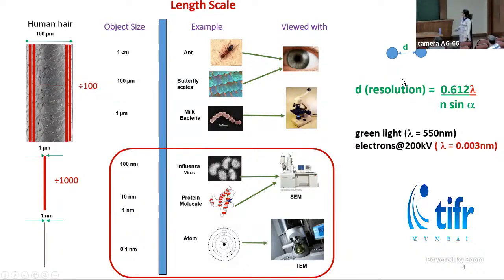It is given by this formula. So by looking at the formula, we can clearly say that the resolution is directly proportional to the wavelength of incident radiation, which is used for imaging. So in case of optical microscope, if we use green light, the wavelength is 550 nanometers, then the resolution will be around 300 nanometers. That means we can see objects of 300 nanometers using optical microscope.